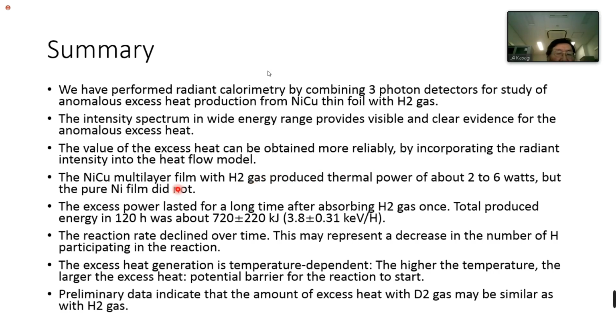flow model. The nickel-copper multilayer foil with hydrogen gas produces thermal power of about 2 to 6 watts, but the pure nickel film did not. Just for the one sample though, the excess power lasted for a long time after absorbing hydrogen gas once. The total produced energy in 120 hours was about 720 kilojoules plus or minus 220. The reaction rate declined over time.